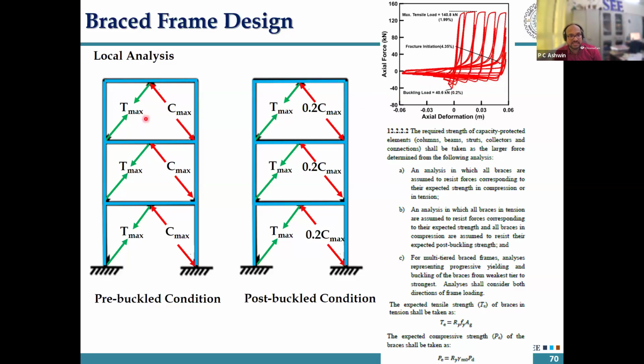So this is Tmax. Tmax is the maximum tension that can come in the brace. So Fy into Ag, you can see here yield strength in the gross cross-section area. But don't forget the uncertainty factor. You have used an E250 grade brace or a 350 grade brace, the actual yield strength might be 300 MPa. So that is what this tension capacity gives you. So you find out Tmax, similarly you find out Cmax. You find out a post-buckle case where the Tmax is still there. The yielding tension doesn't change much, but compression drops down to a lower value, which the code says take it as 0.2 Cmax.